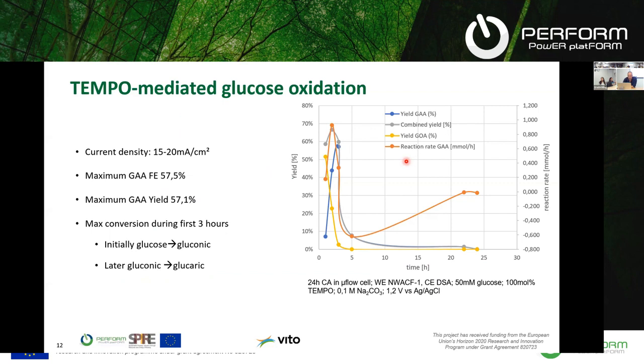When we conducted a test, this is what a batch test would look like. So you can see the yields of gluconic and glucaric acid. But what's important here is to note that there is an average current density of 15 to 20 milliamps per square centimeter. In terms of standard electrolysis, or let's say water electrolysis, this is of course very low, but in organic electrochemistry, this is a reasonable figure. We had a Faraday efficiency of around 60% towards glucaric acid and a yield of almost 60%.